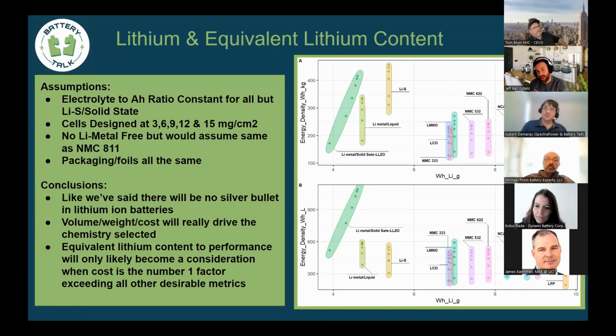Yeah, it's the y-axis that's actually on the bottom graph, your watt hours per liter and your watt hours per kg. The x-axis is basically how many watt hours you get per gram of lithium in a chemistry, right? So there does exist a world where you're getting a very efficient utilization of your lithium to maximize how many watt hours the battery can produce, but it's not really giving you any volumetric energy density. It's just using the lithium really efficiently per unit energy, but it's still a low nominal voltage and it's still a lower density material.